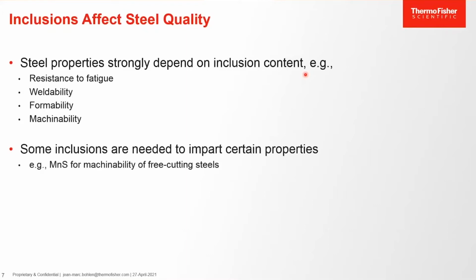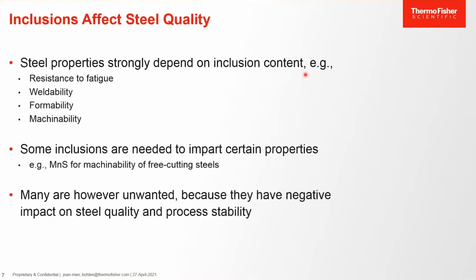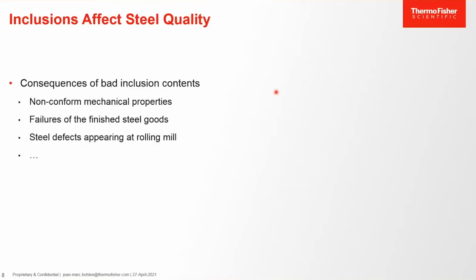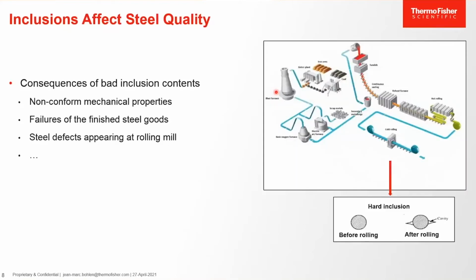Some of the inclusions are needed to impart certain properties. For example, manganese sulfide for machinability of free cutting steel. However, many are unwanted because they have a negative impact on the steel quality and the process stability. What are the consequences of a bad inclusion content? There can be different possibilities, from non-conform mechanical properties to failures of the finished product, or to steel defects appearing at the rolling mill. This is what we see on the picture.